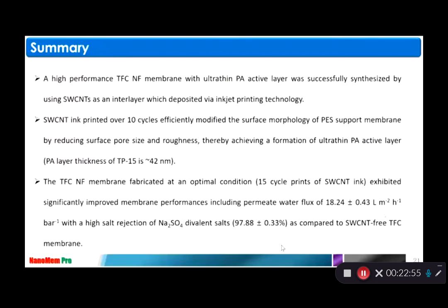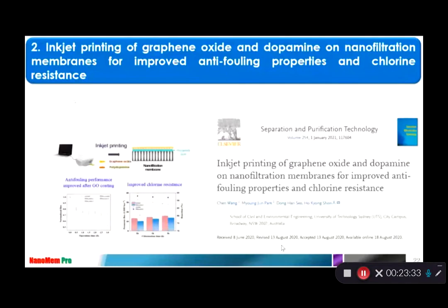So this is the summary. A high performance TFC NF membrane with an ultrathin PA active layer was successfully synthesized using CNT as an interlayer, and SWCNT ink printed over 10 cycles efficiently modified the surface morphology of the PES support membrane. And the NF membrane fabricated at the optimal condition exhibited significantly improved membrane performance, including the water permeate flux and rejection. And this is the overall OSN application, and also we looked at a different application.